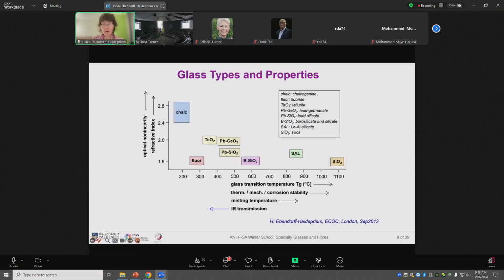So if you now populate this with the different glass types, you see here there are these different glass types. I put here the legend, and the reason is that unfortunately in this corner we don't have a glass. Nature does not allow us. So if you now go through the glass types, there is silica, which has a high Tg, therefore high durability, and therefore it's of interest for high power fiber laser applications.